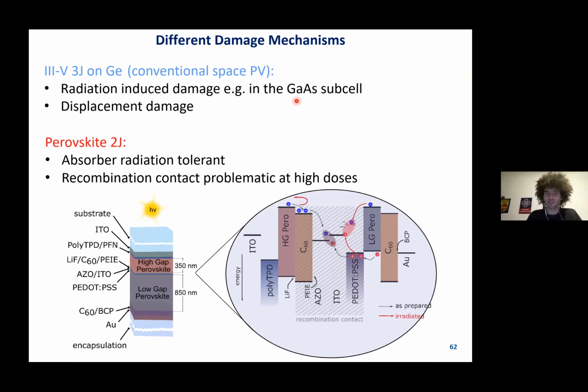So in the gallium arsenide subcell, we see these defect clusters because of displacement damage. But in the perovskite, we know from my experiments on just bare absorbers that they are extremely radiation tolerant, but then the tandem degrades a little bit more. And we, at the moment, think that this is because of damage of the recombination layer.